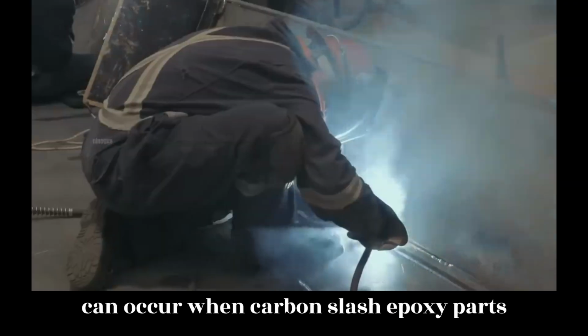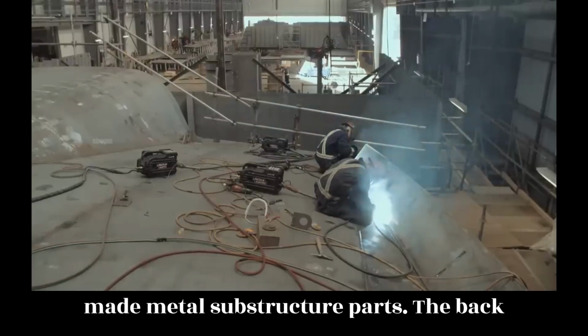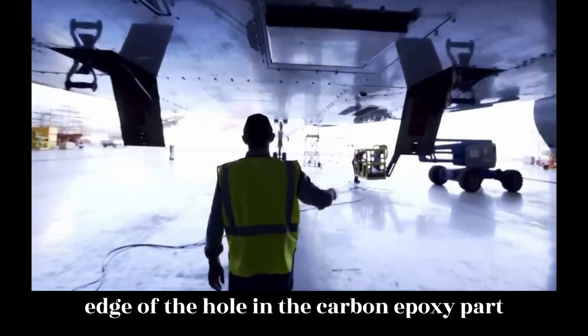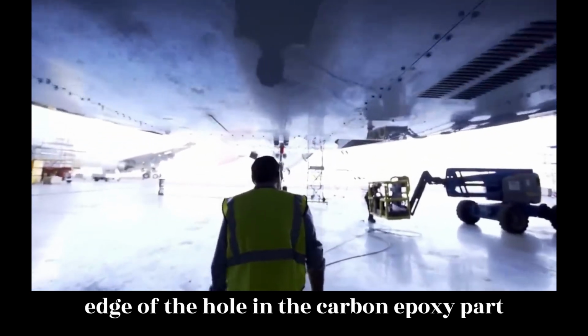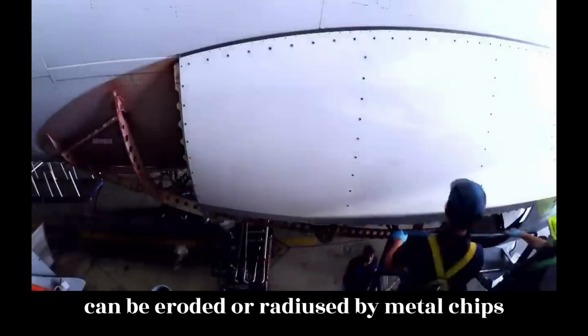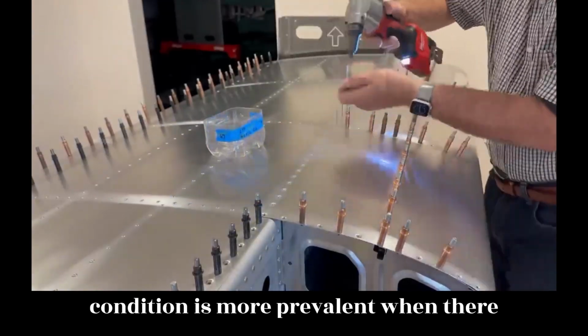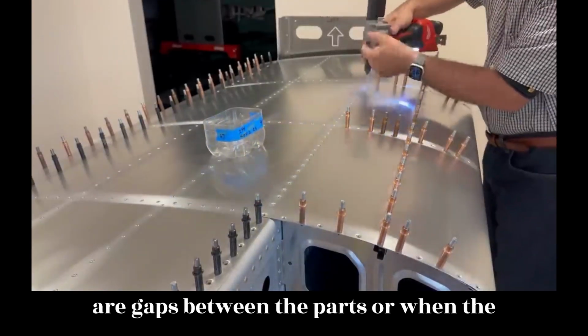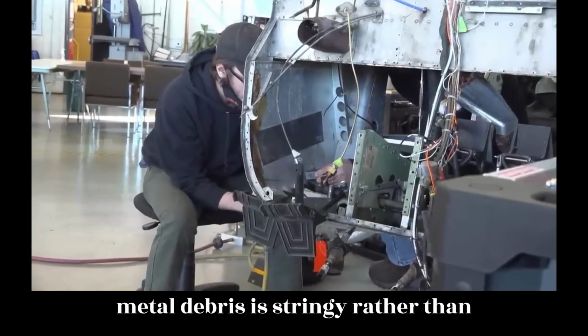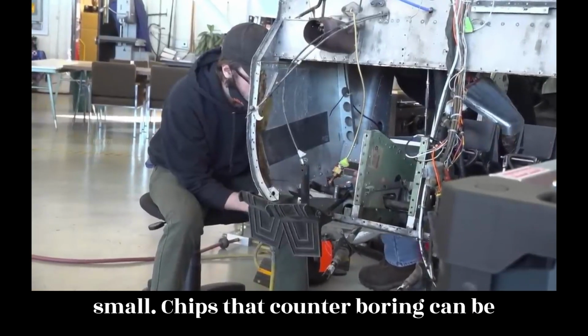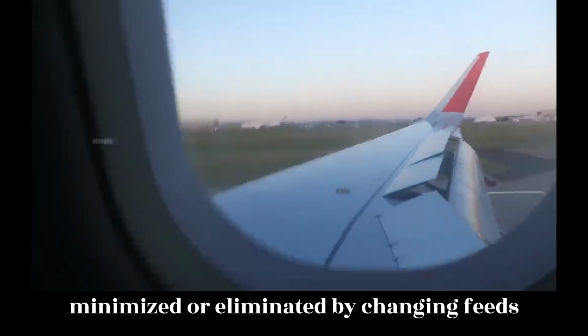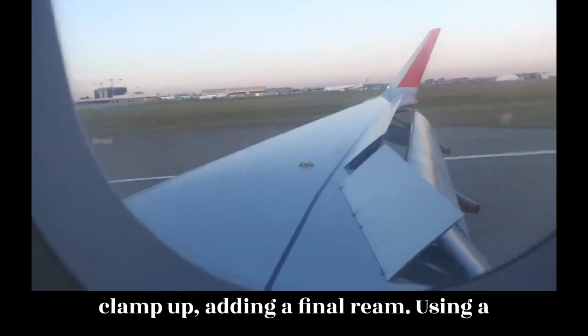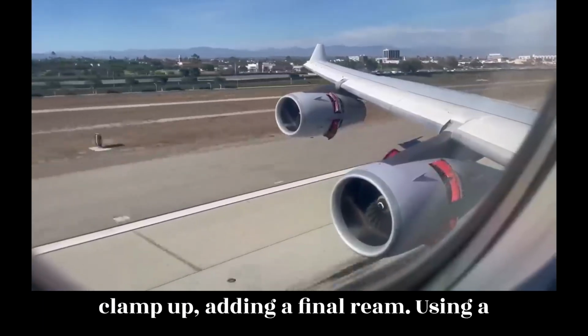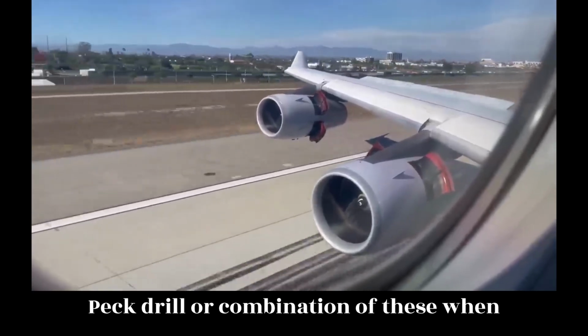Back counterboring is a condition that can occur when carbon/epoxy parts are made with metal substructure parts. The back edge of the hole in the carbon/epoxy part can be eroded or radiused by metal chips being pulled through the composite. The condition is more prevalent when there are gaps between the parts or when the metal debris is stringy rather than small chips. Back counterboring can be minimized or eliminated by changing feeds and speeds, cutter geometry, better part clamp up, adding a final ream pass, using a peck drill, or a combination of these.